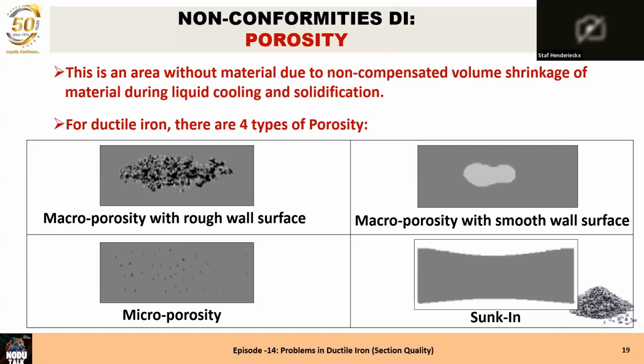So porosity is an area without material due to the non-compensated volume shrinkage during the liquid cooling and solidification. Every material shrinks during cooling and mainly also during solidification. If that's not compensated, it will give a porosity. We have macro-porosity with rough wall surfaces. We have macro-porosity with smooth wall surfaces. We come to the difference later. And we have sunk-in, which is mostly not recognized by most customers and foundries as a shrinkage, as a porosity, but it is.